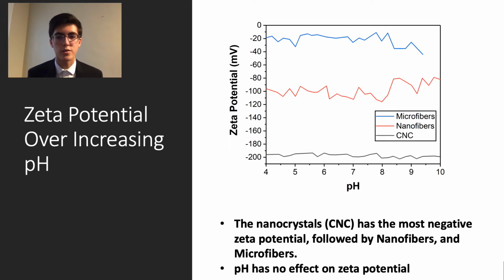The pH value has no significant effect on zeta potential, which confirms the cellulose sulfate charge hypothesis that I had previously mentioned based on the industrial resin data. Now, the reason why this is very important is because when considering the issue of ammonium pollution, as I had previously mentioned, it can be due to things like animal and human excretion, which when you urinate, that solution is filled with protons, and therefore the acidity of it is altered. So you need materials that can remain efficacious through varying acidity levels, and this material offers that benefit.